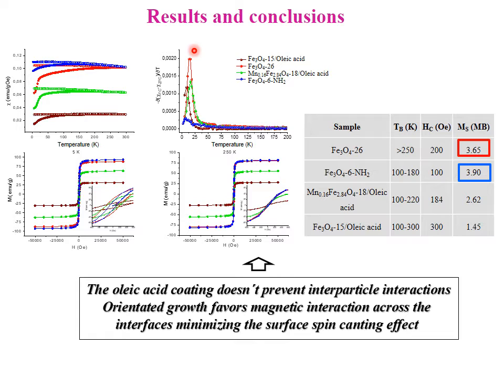The magnetic properties indicate, in all cases, the presence of interparticle interaction in our samples, as suggested by the broad maxima found in the zero field cooled curves, although most of the energy barriers are overcome at low temperature. The curves are indicative that the superparamagnetic regime stands in a broad range of temperature. For the stabilized nanoparticles, this result indicates that the oleic acid doesn't prevent the dipolar interaction between the particles.